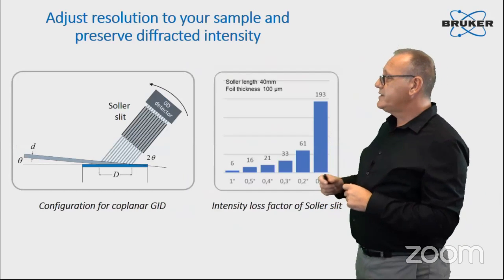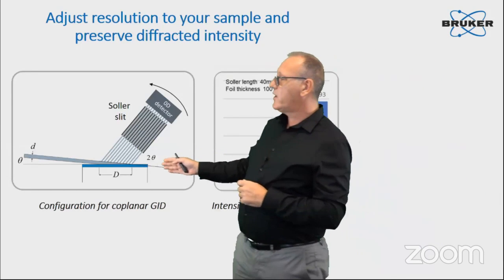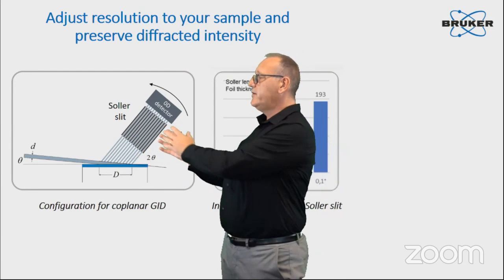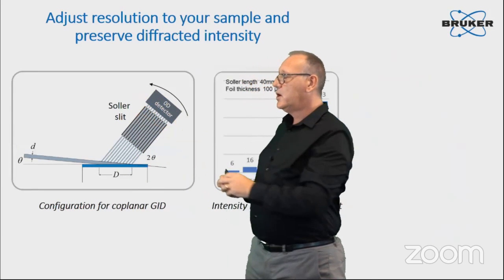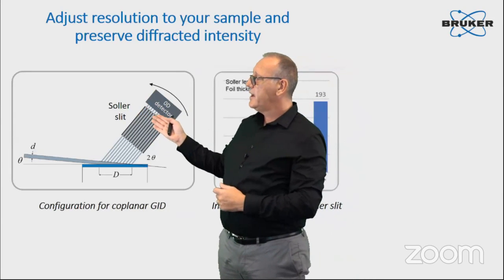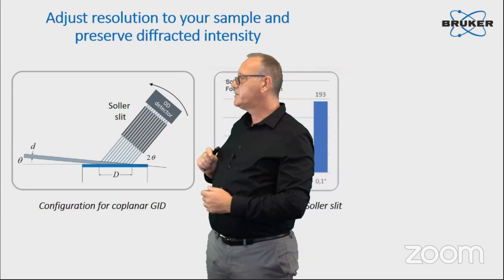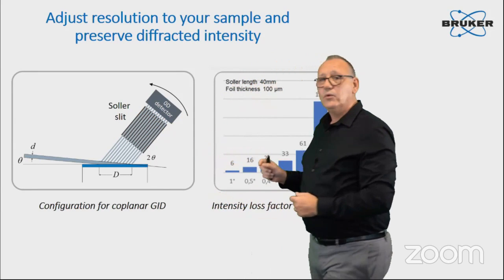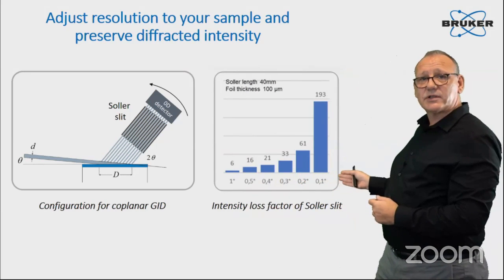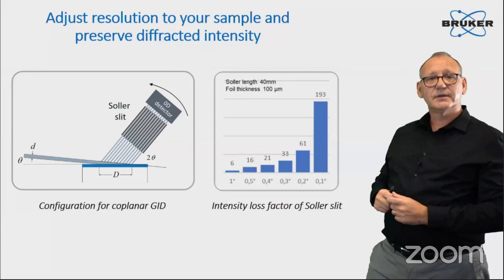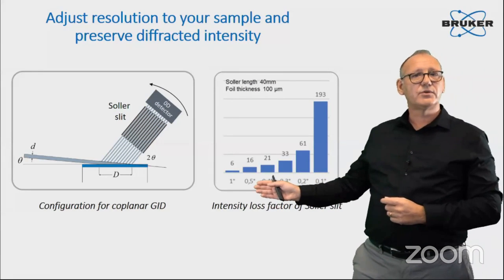If you look here, this is the principle of grazing incidence diffraction. You have a pretty large footprint, so the diffracted beam will be very broad and in all directions. So you need collimator plates like displayed here in order to precisely measure a certain 2 theta position. We have a very large set of different angular acceptance. So this defines your instrumental resolution.